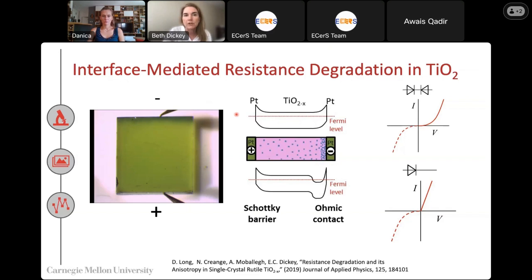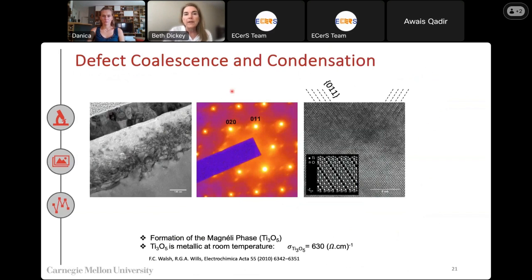The other thing I'll show, and I mentioned before, is if you look under those electrodes where it looked very dark optically, here's the electrode, dense platinum. This is that single crystal of titania. If you do electron diffraction, you see superlattice spots associated with all of this contrast here. You can see ordering of defects and actually the formation locally of these Magnéli phases, which are very substoichiometric.